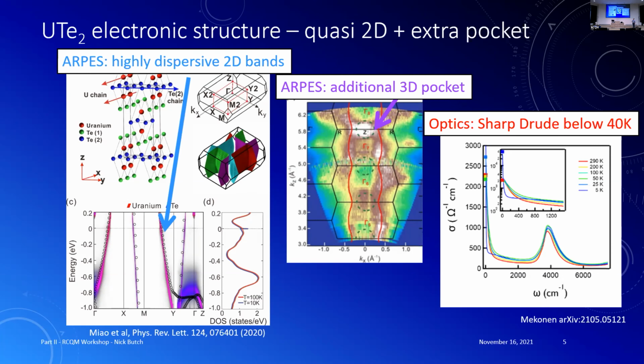Now this was done at 20 Kelvin, so it's also a question of energy resolution, but there aren't really strong indications of f weight if you're just looking at this. There is actually f weight at the chemical potential. And then there's a sign of an additional pocket that doesn't seem to be directly predicted by any of the first principles calculations. So that's the best we know right now. And optical conductivity from our friends at Hopkins shows that there's a very nice Drude behavior, especially below 40 Kelvin. So it's proper to think about this as a heavy fermion, Fermi liquid compound.